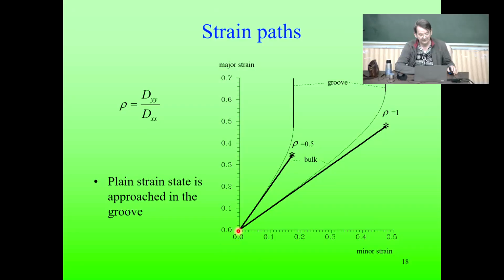So we impose in the simulation a constant strain path, you see, that we just deform the material imposed on the sheet. So the state in the region A is moving on this line, and region B, we obtain the solution, how the deformation is going on. Deformation is deviating already from the beginning slightly, and then it's increasing. At a given large strain within the groove, the deformation is deviating so much that it becomes plane strain, so that only the major strain is developing and the minor strain is zero.